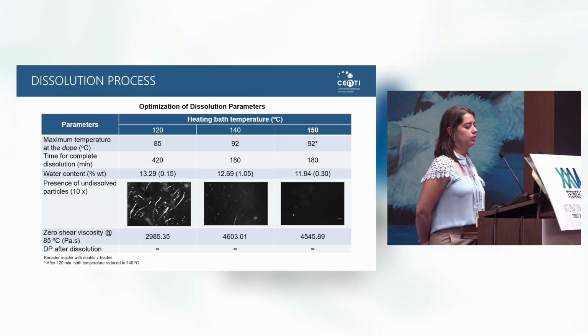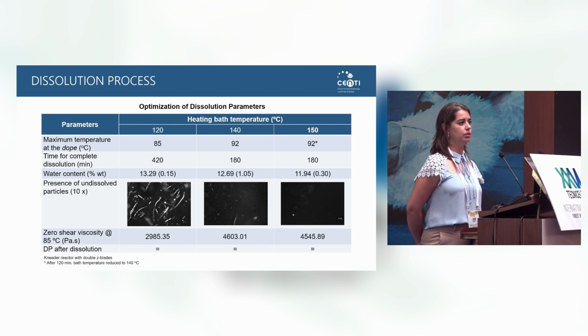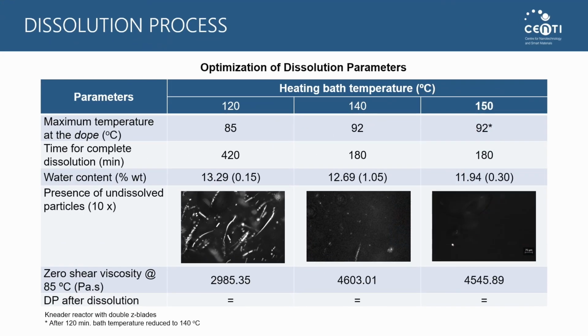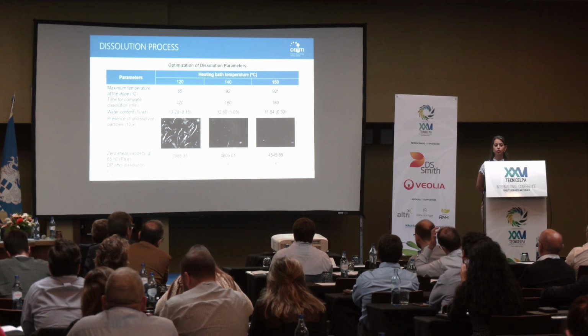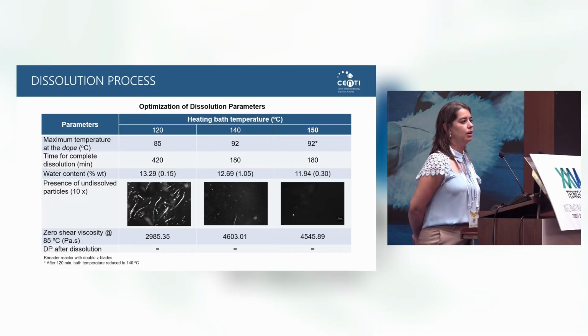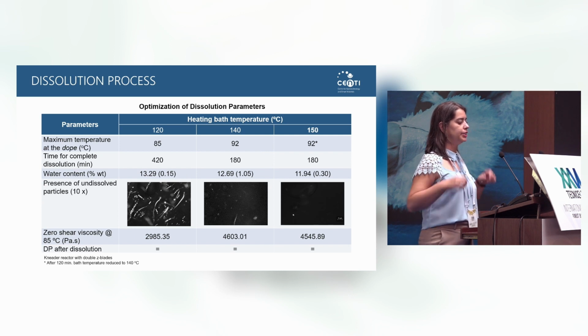After that, we started the dissolution of the cellulose. We did optimization of the parameters of the solution. We used N-methylmorpholine N-oxide as a solvent. It is a direct solution, so we don't need to derivatize the cellulose. Our main control parameter is the temperature. We have to be careful because NMMO can degrade and also degrade the cellulose, so we take care of the heating bath temperature.